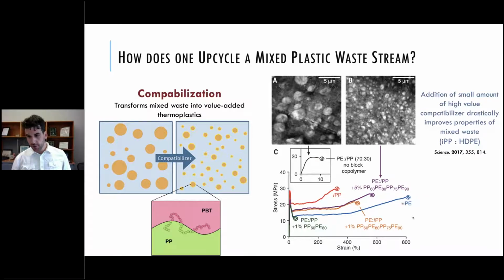If you look at polyethylene, right, one of the reasons it's so valuable is because it's reasonably strong, but you can extend this out to about 800%, so 8 times its original length, before it'll break. Polypropylene is stronger than polyethylene, and you can extend it out to about 3 times its original length before it breaks. So if you compatibilize these materials, you can actually get compatibilized plastics that have properties in between that of polyethylene and polypropylene. So if you add 5% compatibilizer, you can see, or if you add 1% compatibilizer, that's better. You can now extend this mixed material out to about 5 times its original length before it breaks, and it has a strength that is higher than polyethylene but lower than polypropylene.